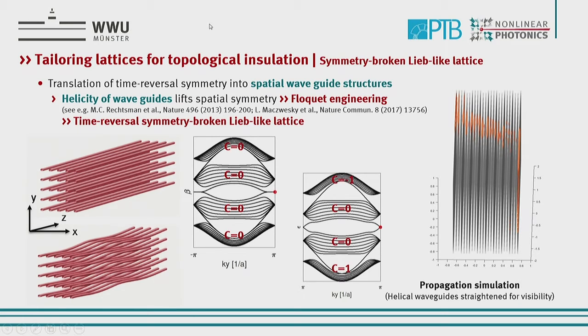And this can be done by modulating this waveguide in a sort of wavy way. This means you break the symmetry, and this also breaks the symmetry in the band structure, because you see now that you have Chern number 1 and minus 1. So from 1 to 0 and from 0 to minus 1, you have a change. And this exactly gives this phase transition.